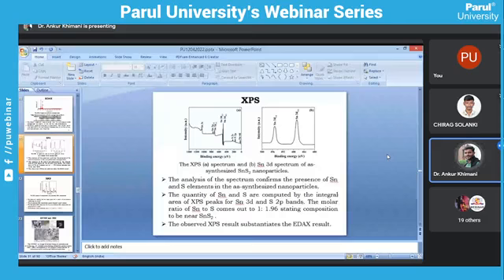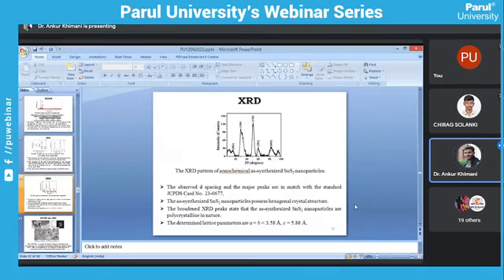So XPS gives the bands. The molar ratio of Sn and S comes out 1:1.96, stating the composition to be SnS2. So this confirms we have grown the particular particle. That the particle is SnS2 is confirmed by EDX and XPS. The observed XPS result for SnS2 substantiates the EDX result.